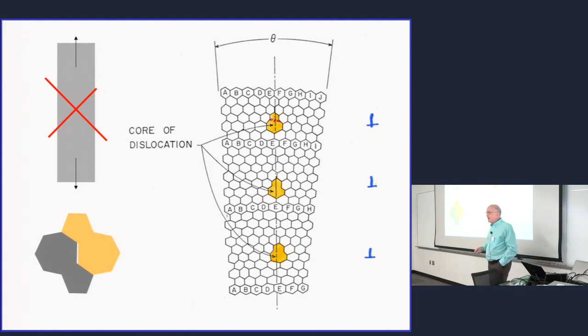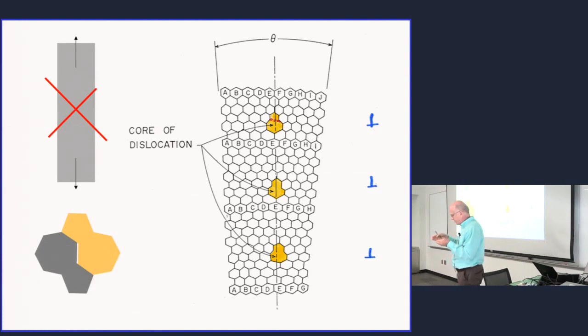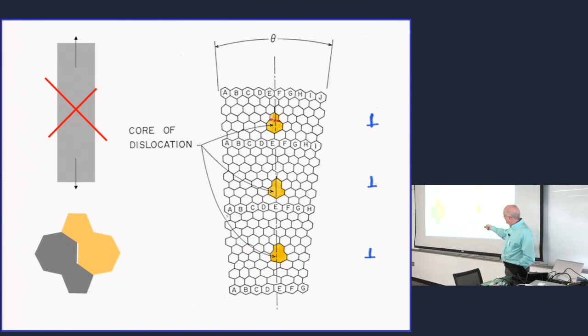Then it means that under very high tension, the yield of the material should be motion of these objects, glide of dislocations, okay? And if you have a perfect lattice, like a nanotube, we think it's perfect, or at least we want it to be perfect, then first you have to create a dislocation dipole. And then you just figure out how a dislocation dipole should look. If this is one dislocation, then a dislocation dipole should look like one of them and then an inverted twin, right? You just invert it and together this is a dislocation dipole. So it should be structured like this, and if they form somehow under tension and high temperature, then they can start moving, and that would be your mechanism of yield.